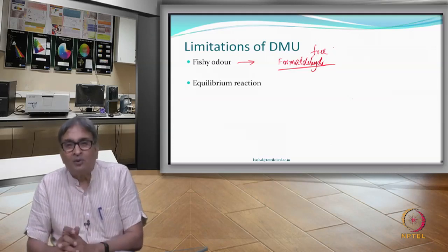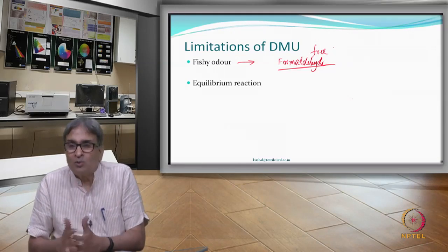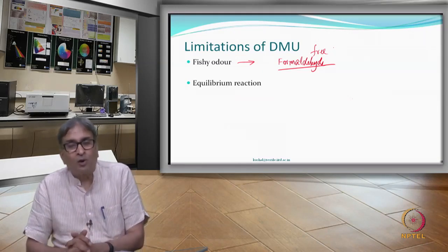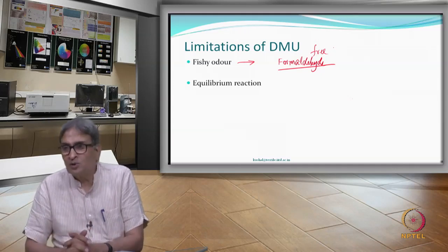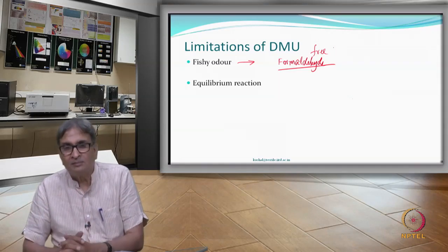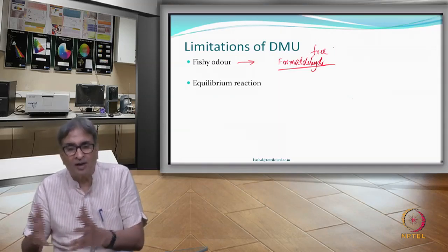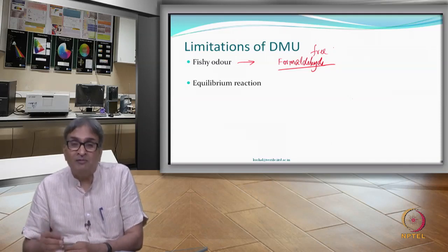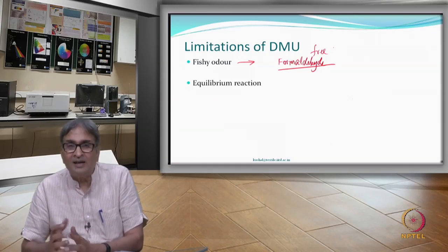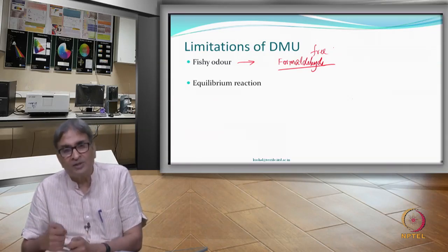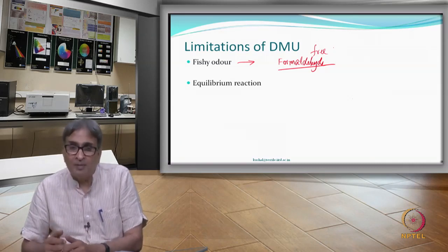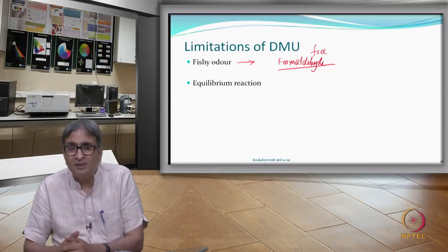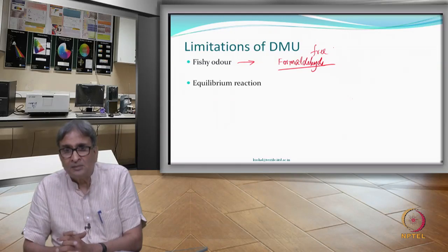But another equilibrium consideration is that every reaction, although strong, can also undergo a reverse hydrolysis reaction. If you wash a fabric treated with DMU, a reverse reaction is also possible. When it hydrolyzes, free formaldehyde can be generated in washed fabrics, stored fabrics, or fabrics kept in moist conditions for a long period. So when you open it, you smell it — people did not like that.